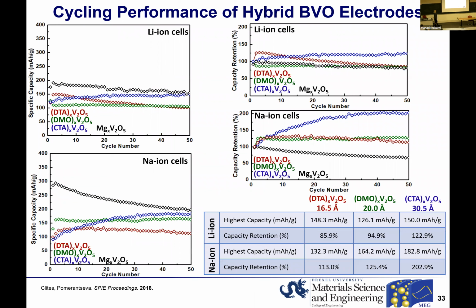However, what's interesting is that we expected to see huge capacities because we have such large interlayer spacings. But no, just the geometrical factor is not sufficient to achieve high capacities in battery reactions, because we also need the transition metal ion to reduce, and the number of transition metal ions is fixed.